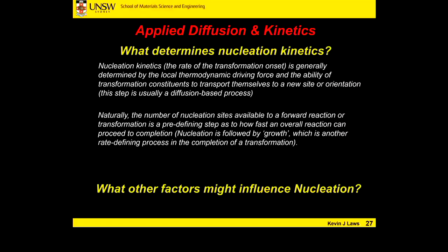Yeah, so a grain boundary in a material, okay, often we get precipitation at a grain boundary, boundary migration happens at a grain boundary, okay, and that's again associated with energy. The structure at the grain boundary is actually disordered. We've got two crystal lattices, different orientations butting into one another. Okay, where they join, the atoms have to try and bond as best they can over that grain boundary. It's a high energy location. Right, all materials, natural materials, want to reduce their energy. Right. So a high energy site is a good place for nucleation to occur, so the material can reduce its structural energy.